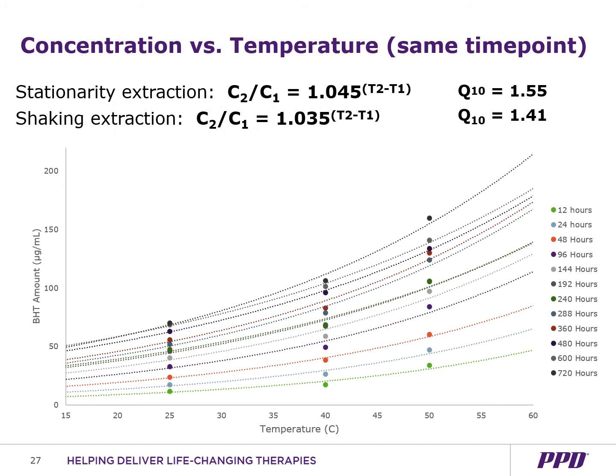From the data, we were also able to develop a concentration projection model related to temperature for both shaking and stationary results. In this plot, we have a summary of the shaking results, where we have the BHT concentration plotted against the extraction temperature for a given time interval. We were then able to use the equations generated by each curve to generate a concentration equation shown at the top, where a projected concentration, or C2, over a known concentration, or C1, equals a constant raised to the difference in temperature. For the stationary results, our constant was calculated to be 1.045, and for shaking, we got 1.035.